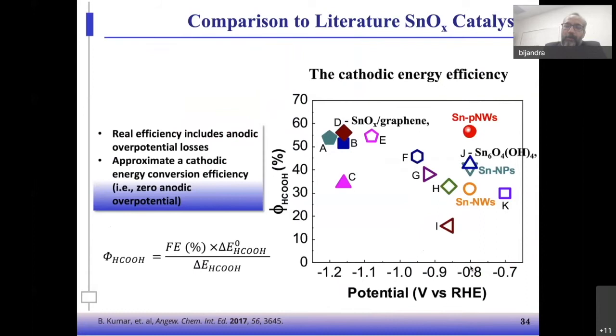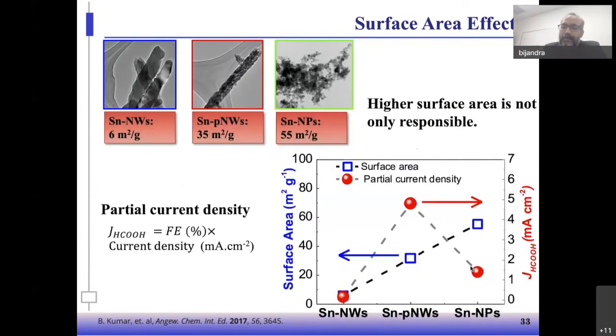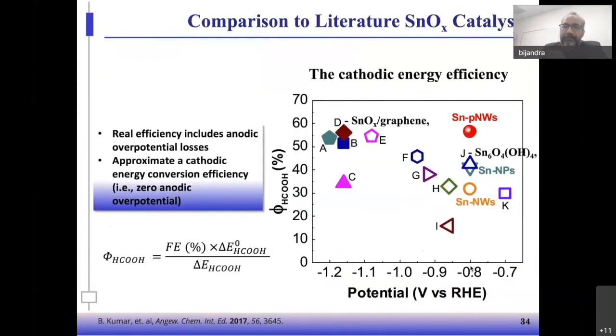And when we did more characterization, we came to the conclusion that this porous nanowire has a defective structure where two different types of grain are merging and creating a lot of grain boundaries. And due to those grain boundaries, they have shown really high performance. Overall, when we compare the result with other catalysts, the cathodic energy efficiency of this catalyst is really high at low potential. So that was another type of catalyst we can have.